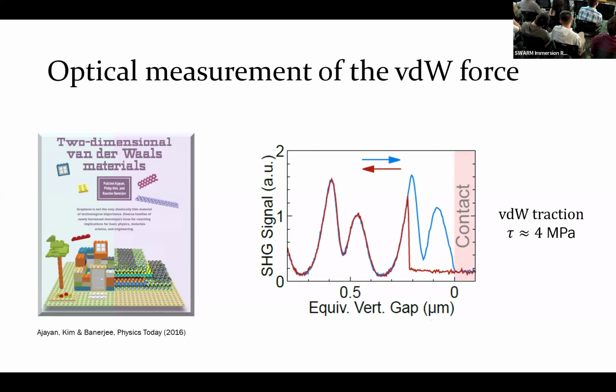And this will show you, when we apply the electrostatic motor to get into contact, and then we remove the voltage, there will be a hysteresis before the interface starts to move. And that's because there is a van der Waals traction between the two interfaces. So you first have to overcome the van der Waals force, and then the interface would all of a sudden jump to some distance. And that's what we're seeing here in these measurements of the second harmonic generation.